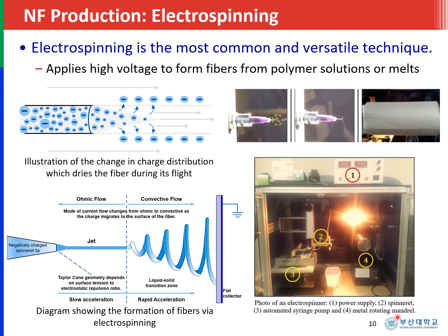This photo shows the electrospinning system that I use in my experiments in making nanofibers. Typically, an electrospinning system is composed, of course, of the high voltage power supply, spinneret, here too, and higher magnification of that is this one. We have an automated syringe pump and a collector. In our case, we use a metal rotating mandrel because when you have a metal rotating mandrel and not a flat plate stationary collector, it is moving, so it's spinning. So when it's spinning, it will also help in fine-tuning or creating quality fibers.